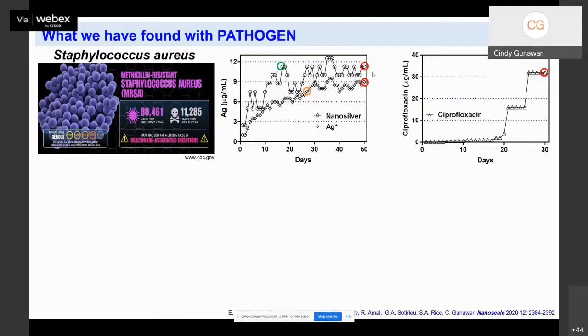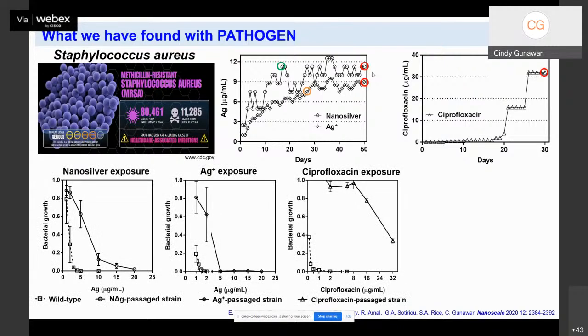After the antimicrobial-free culturing, we then retested the minimum inhibition concentration of each of the antibacterial agents on the passage bacteria here. So this is the result for the nanosilver. The dotted line here is the growth profile for wild-type bacteria when exposed to increasing concentrations of nanosilver. It means the bacteria that has not been pre-exposed to silver nanoparticles.